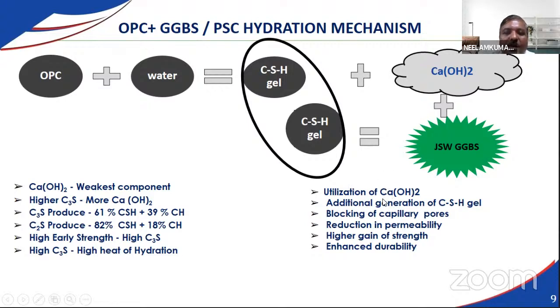So we can utilize this calcium hydroxide from the secondary hydration point of view. So additional generation of CSH gel, that is calcium silicate hydrate gel, is formed, and it gives further strength on the later ageing of the concrete. So this blocks the capillary pores which are formed in the concrete matrix. Because of this blocking of the capillary pores, there is a tremendous reduction in the permeability. So one can get the impermeable concrete.